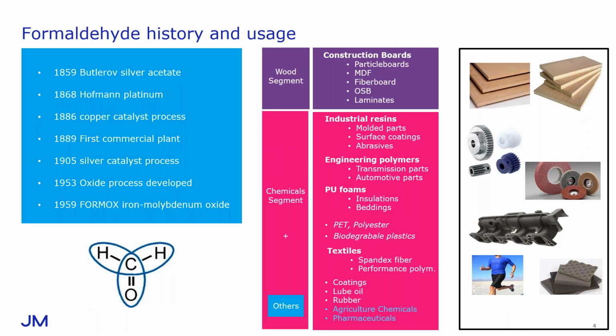Formaldehyde has a long-lasting history, and it goes back to the 19th century, where the Russian and German scientists Butlerov and Hoffman were performing experiments on a laboratory scale. They were oxidizing methanol to formaldehyde. This was then further developed through the years, and in 1959 the first commercial scale plant was set up and started in Sweden, where we had and are still using an iron molybdenum catalyst in a tubular reactor, with a gas phase reaction taking place. This formaldehyde, which we have in the gas phase, is then further absorbed in a liquid, water, and the product is then called formalin.